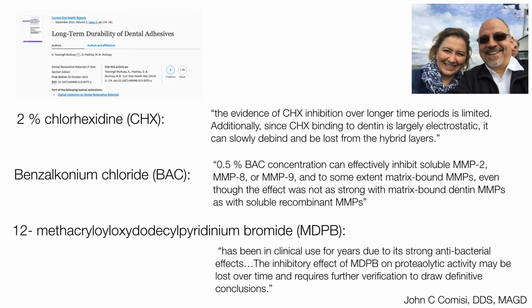Now, chlorhexidine 2% has been suggested and used extensively over the course of time, but its bonding is largely electrostatic and has been shown to be not very long-lasting. Benzalkonium chloride, BAC, at 0.5%, has also been advocated and has been shown to tie up a lot of different MMPs, but it's not strong enough against the matrix-bound dentin MMPs. MDPB is another agent that has been suggested, and as it is stated, has been in clinical use for years as a strong antibacterial, but also loses its benefit over time.